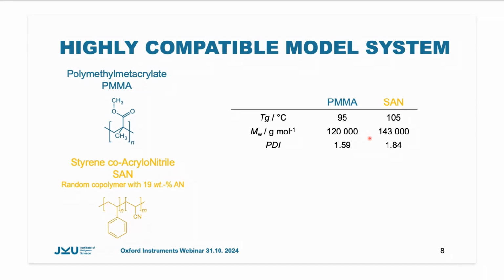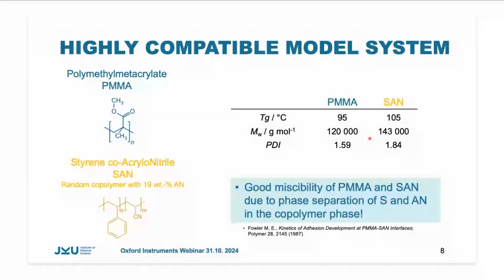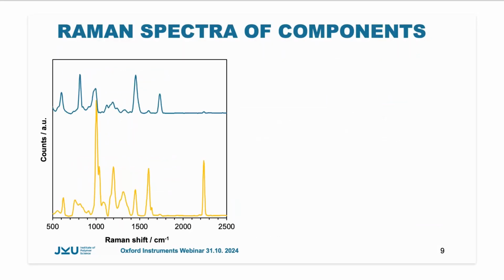From the first glance, when you look at the polymers and you see that you have styrene and PMMA, they are normally not compatible. Why can we mix PMMA and SAN? Because in the copolymer, the SAN, styrene acrylonitrile, there we have a phase separation which favors the incorporation of PMMA. Thus, we get a very good compatible system for further investigations.